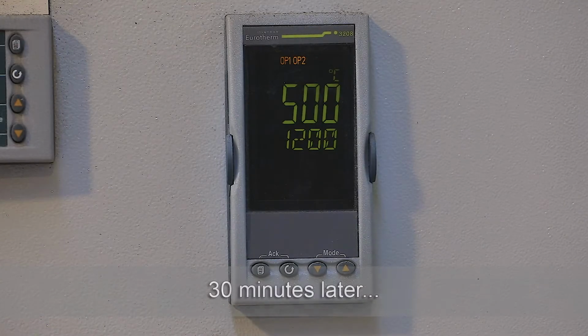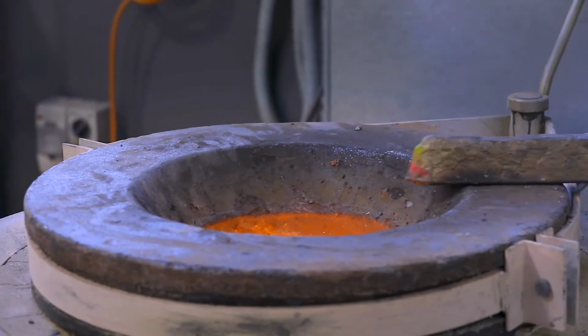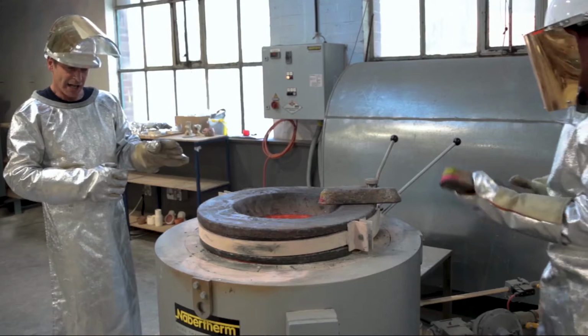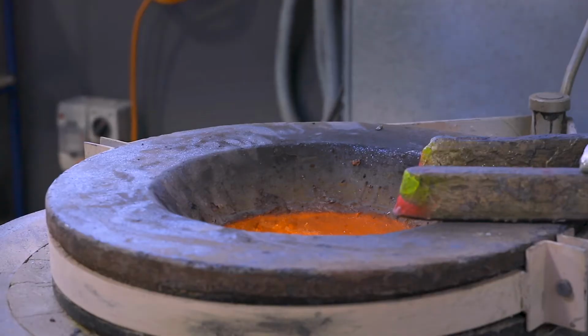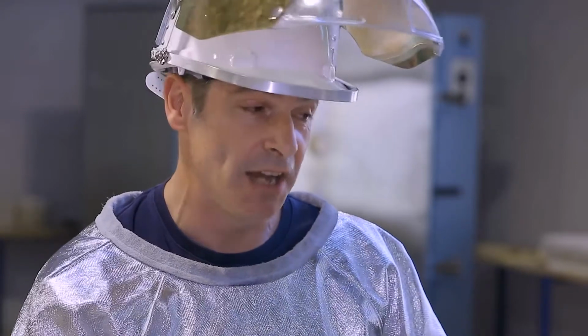Now that we're up to 500 degrees, we'll start to pre-warm the ingots on top of the furnace there. The reason why we pre-warm them is to make sure there's absolutely no moisture. If there's even a drop of water, when we put them into the molten bronze, the furnace will superheat the water so quickly that it'll expand and explode. So safety first, we'll make sure everything's toasty and warm.